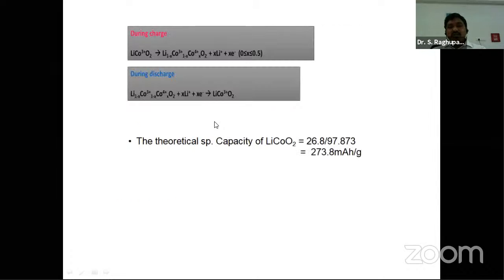Now, how does the chemical reaction take place? In LiCoO2, during charge, lithium comes out from LiCoO2, and it becomes Li1-xCoO2, as x lithiums come out. And the cobalt here is in the 3+ oxidation state. As lithium goes out, the x amount of cobalt has to adjust its charge to 4+ for charge neutrality. But the maximum lithium that can be removed is up to 0.5 lithiums.